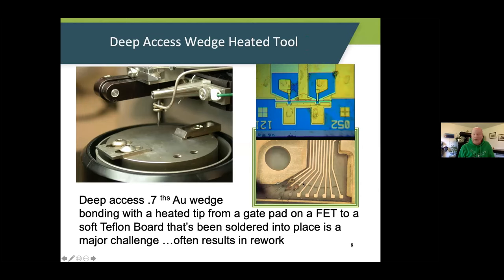And then on the other end, you're going to bring it down to a Teflon board. You're probably familiar with the Rogers materials and other people make them, but Teflon is loaded with ceramic, so if you get a version that doesn't have a lot of ceramic, lower dielectric constants, it can be much softer. And if you heat it, that makes it even worse. And some boards get soldered in place, so you can't just put it through a board washer and expect it to be clean enough.